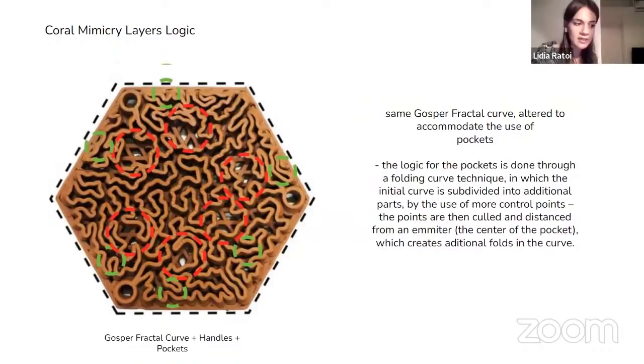And this was a challenge because once again, when we created bigger openings, we would have incohesive drying. So we made this folding pattern. So whenever there's a pocket, the line right next to it gets more dense to counterbalance the scarcity. So we also included these special handles in the patterns, which would signal the location of the legs because we couldn't just put the tiles on the bottom of the water. We had to print legs for them as well and elevate them slightly because there's sediment on the bottom of the water and the ground is uneven. And all ridges and trenches were at least 2.5 cm wide so that the corals can grow within them.